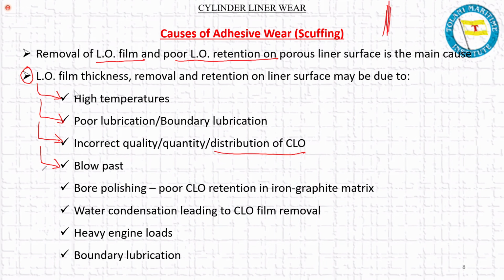Definitely, I told you if a high amount of lube oil is sent with high alkalinity content in the cylinder lube oil, then all of this lube oil may not get consumed, and it will form a lot of ash deposits on the piston ring lands, which can cause bore polishing of the liner. Bore polishing means the liner bore internals are getting polished, and the honing marks which are there on the liner surface are getting converted into a smooth mirror-like surface. And a mirror-like surface will not be good for retention of oil, and increased wear will take place.